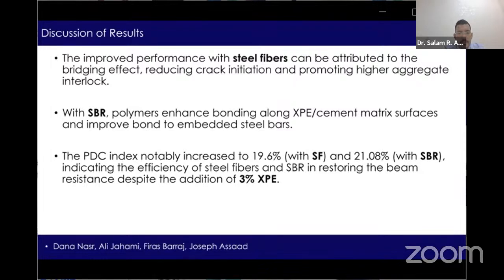Finally, it was shown that the post-diagonal cracking index remarkably increased. It became pretty close to the control mix when steel fiber was used, and it even surpassed the value of PDC corresponding to the control mix when SBR was used in the mix. So we can say that these results indicate the efficiency of steel fibers and SBR in restoring the beam resistance after the formation of the first diagonal crack, despite the addition of 3% XPE plastic waste.